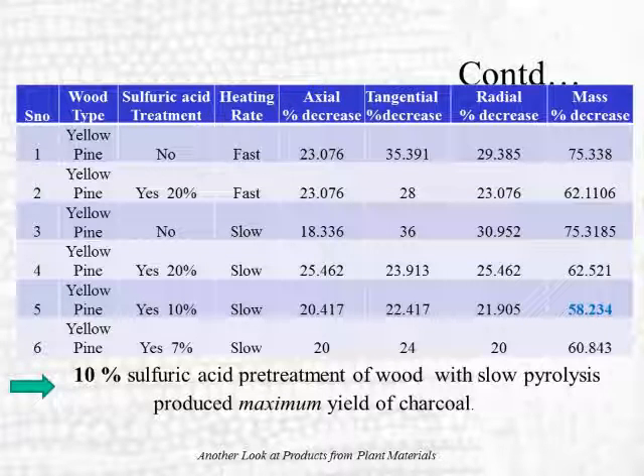they tend to decompose at different temperatures, with the hemicellulose going at the lower temperatures on average, the cellulose decomposing at a little bit higher temperatures, and the lignins going at the higher temperatures still. So you would presume different compounds in the different temperature ranges. But I don't know them well enough to be able to articulate just which ones they were.